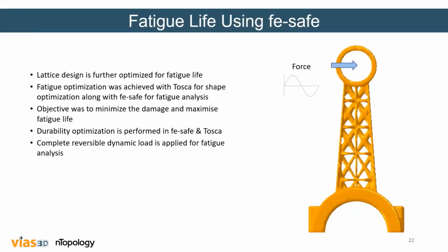And then at each nodal point, it will calculate the damage, and with the damage values from all the nodal points, it will choose which one is the worst scenario and report that as the fatigue life of the structure, because all it takes is to initiate one single crack, and that can fail the structure. So based on that philosophy, Fesafe gives you this output of the fatigue life. Going to the next one.